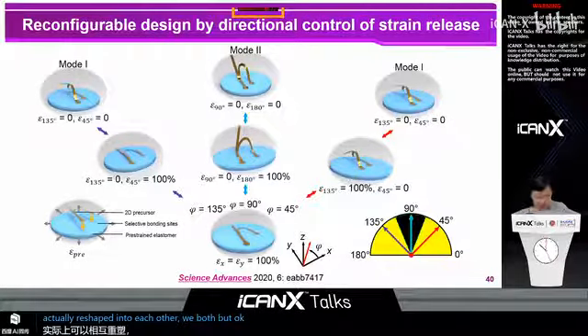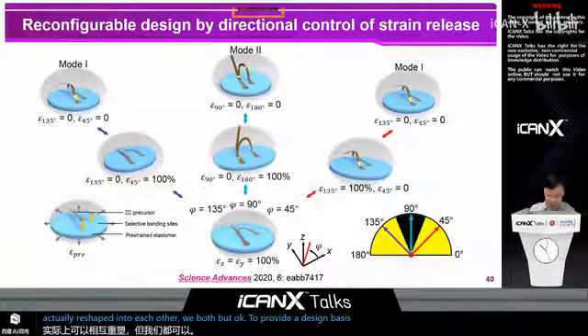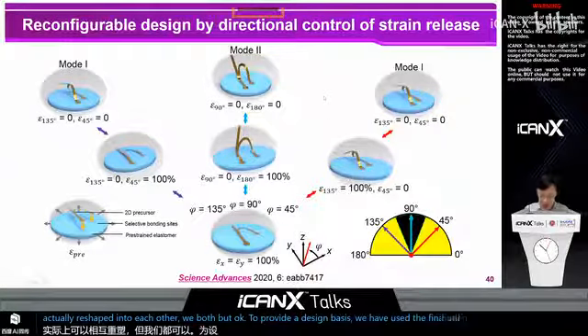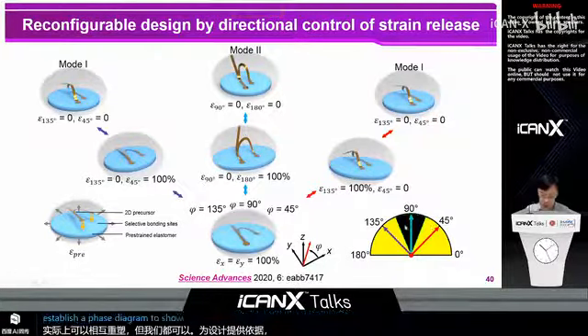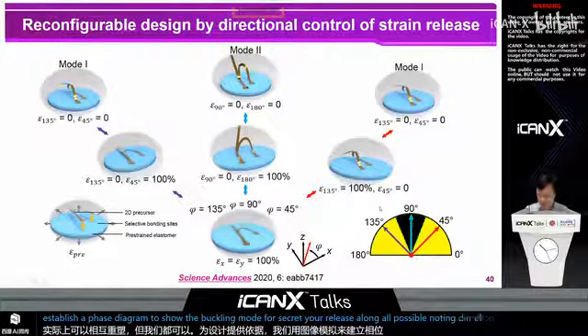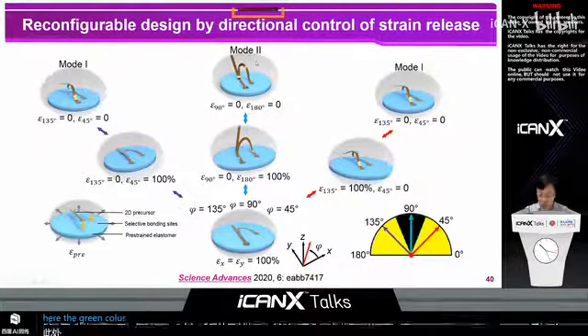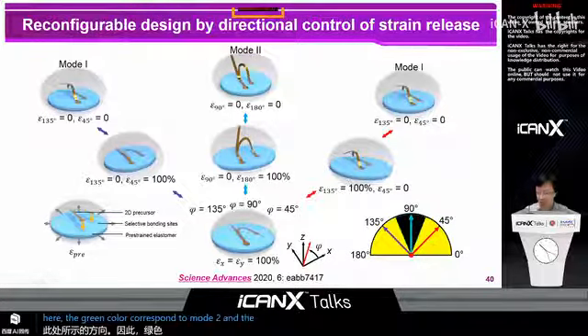To provide a design basis, we have used the finite element simulations to establish a phase diagram to show the buckling modes for sequential release along all possible loading directions, as shown here. So here, the green color corresponds to mode 2, and the yellow color corresponds to mode 1.